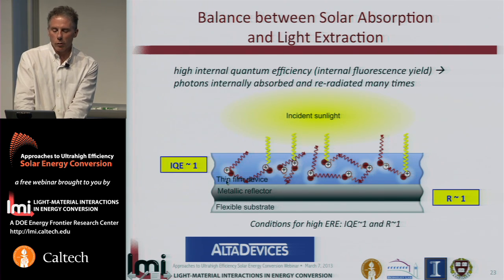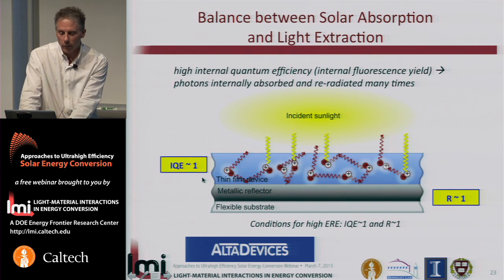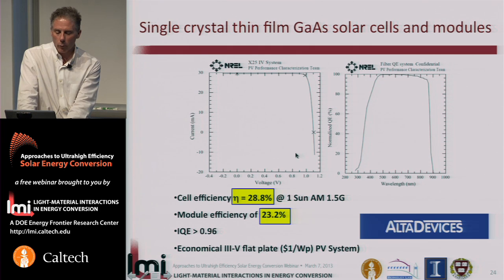And this is a great prescription for internal photon recycling, which has the same effect as increasing the optical concentration by the light trapping techniques that I described earlier, but doesn't necessarily require a nanoscale texturing to achieve this enhancement. It's due to the internal radiative emission that causes photons to be recycled between electron hole pairs extensively in this high radiative efficiency material. And that allows one to make, and this is a series of records that have been set by Alta Devices for open circuit voltage and efficiency in these thin film gallium arsenide cells. This depicts the current voltage characteristics of the record single junction cell at 28.8%.